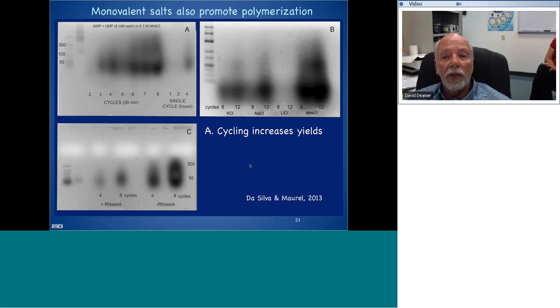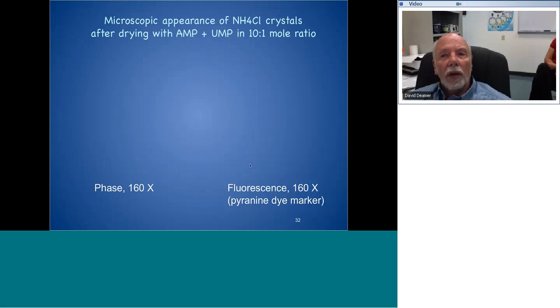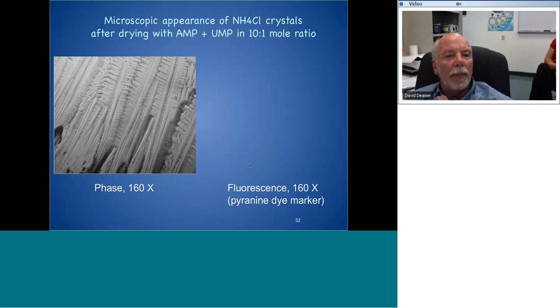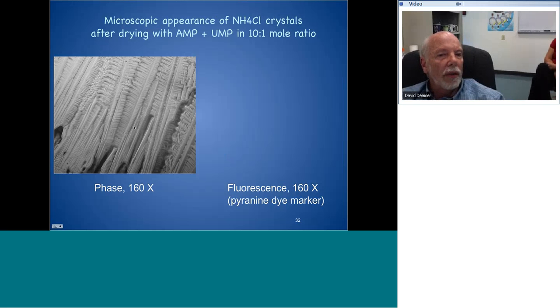So we're pretty sure that we have what everybody, I think, would call an RNA-like molecule being produced under these conditions. Summarizing, cycling increases yields. Ammonium chloride is the most effective promoter of this reaction. RNase digests the product. So now I'm going to show you why we think these salts might be working. The reason is that we think they're doing something like the lipid did. Here is a phase micrograph image at 160 times, relatively low magnification, of that thin film of ammonium chloride plus AMP and UMP on the bottom of this little reaction vessel.